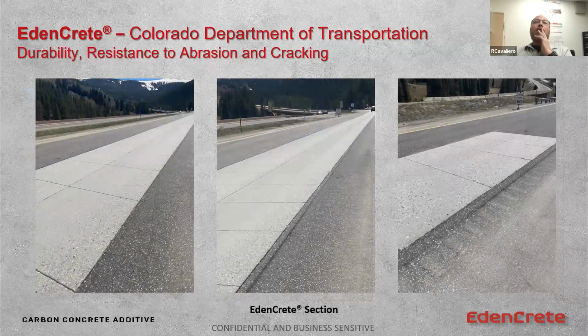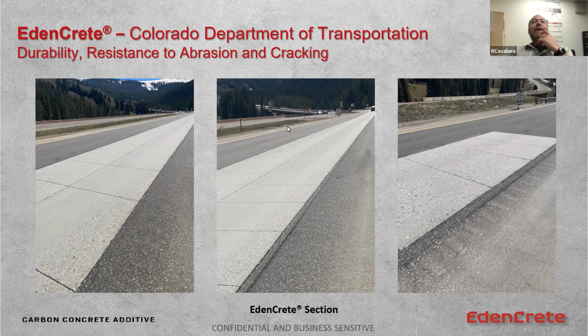And the EdenCrete, we have no cracking. We've got a minimal amount of abrasion down here on this far end. And in the middle section, it is much less. And then over here, we've got a little bit more, but we have no cracking within the field or on any of the edges. And so we're 1 year into a 3-year evaluation.